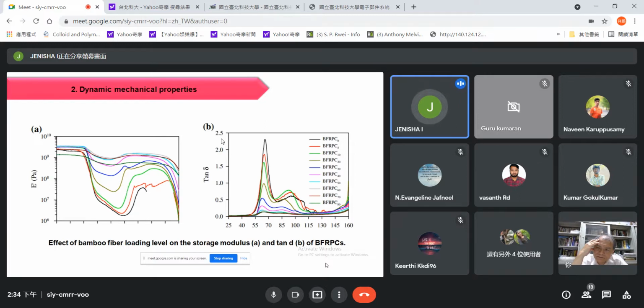Also, in the second figure, we could see that the different loadings, that is from 0 to 80, are plotted. So here we could say that at 98 and 135 degree temperatures, we could see peaks. These peaks also represent the amorphous and the crystallite structure.